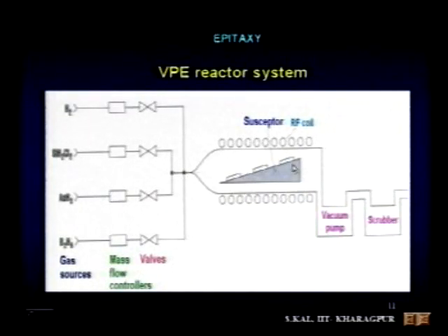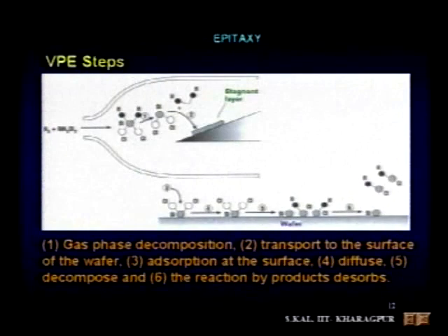You see how the susceptors are kept. So in this susceptor configuration, the stagnant layer or boundary layer problem is minimized. I cannot say it is nil, but it can be minimized in this fashion. And that angle is of the order of 3 to 5 degrees with the horizontal line. Okay. So now, let us discuss